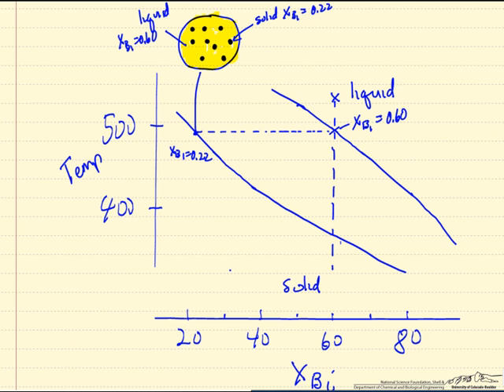However, as we continue to cool, what happens is going to end up being non-equilibrium because we cannot cool it slow enough in typical operations. We're cooling it too fast for solid diffusion to keep up. So let's look as we get down to this point here.